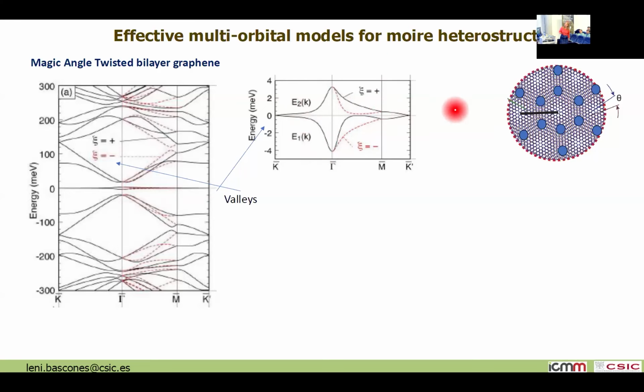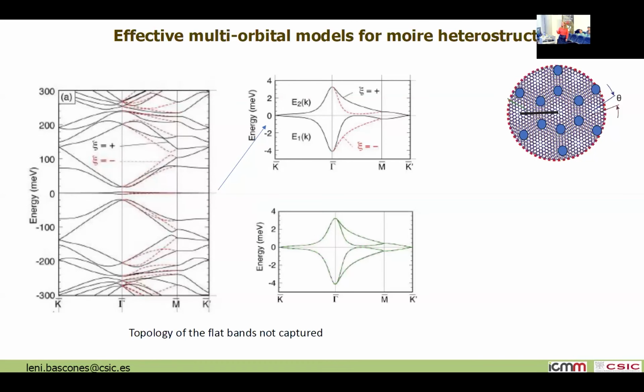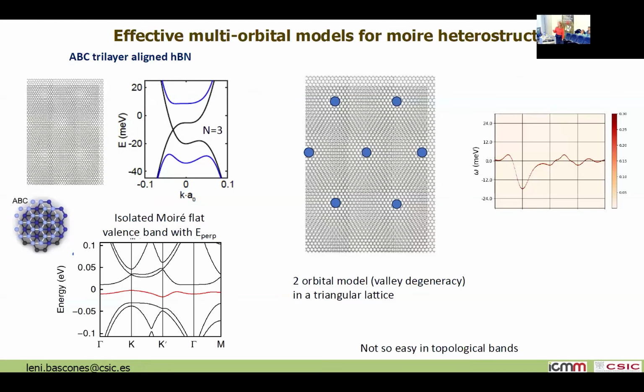So the question is, people tried to say, okay, can we build a multi-orbital model only for these two flat bands? Well, people really did some fitting and got this. You will say, well, it looks great, right? It is not. Something interesting here is that when you look at where the charge is, mostly the charge is concentrated in the real system at the center of this Moire unit cell, similar to here. One thing is that these orbitals that I have put on this triangular lattice are centered at the same place where the charge accumulates. So here, in these two layers, the charge of these flat bands is not homogeneous in the Moire unit cell. It's concentrated mostly at the center of the unit cell.